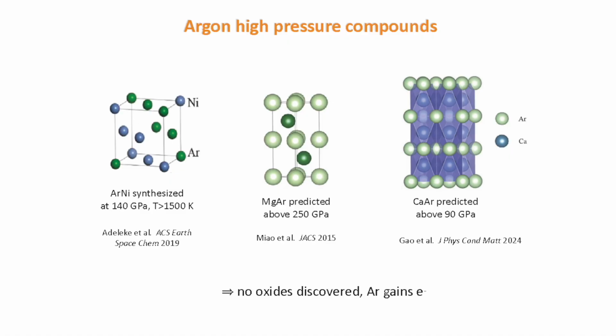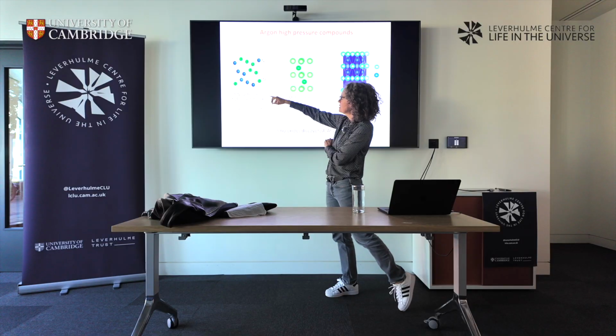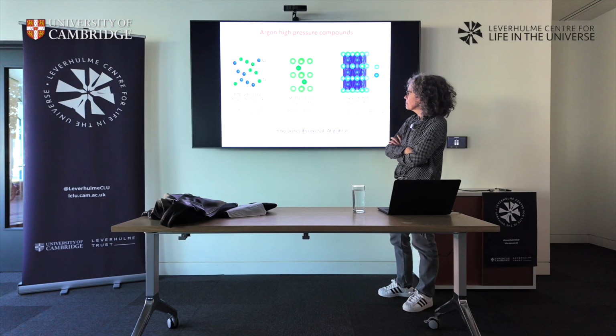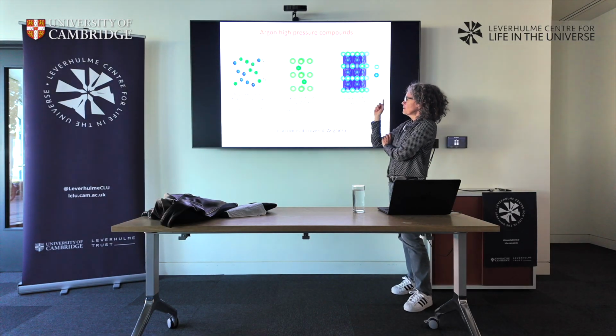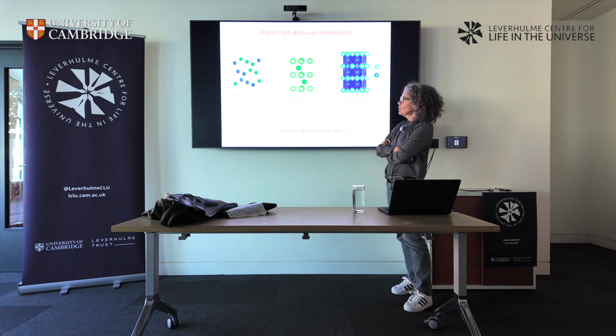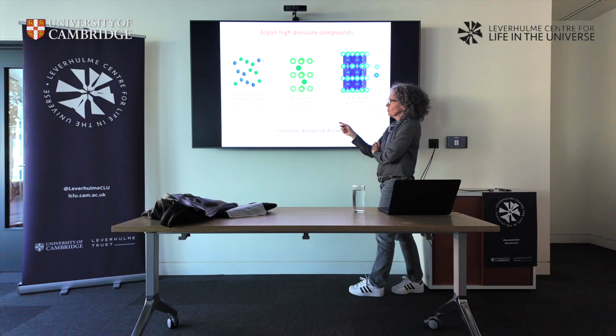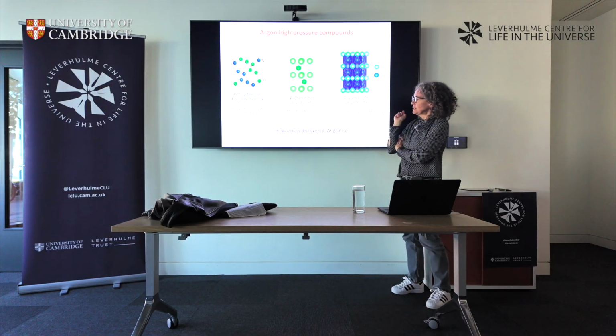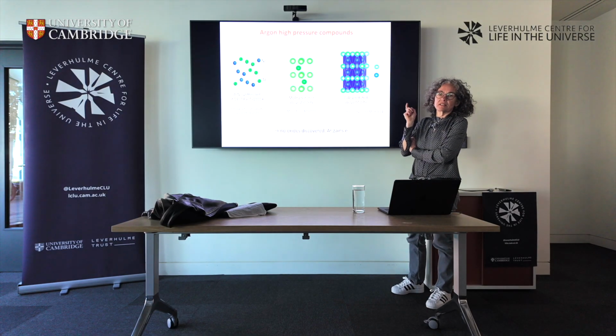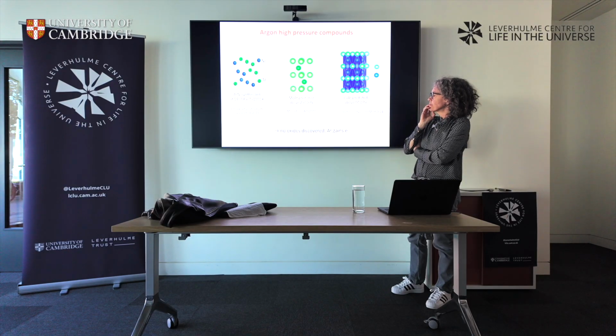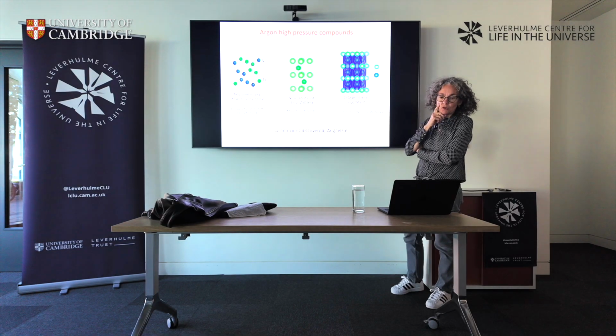This is the only material that has been synthesized so far in a diamond anvil cell, argon nickel. A few others have been predicted by ab initio calculations at quite high pressures. In all three cases, there are no oxides. So far, really no oxides, whatever the conditions. It's more the other way around: argon gains electrons, doesn't want to give electrons, it looks like.